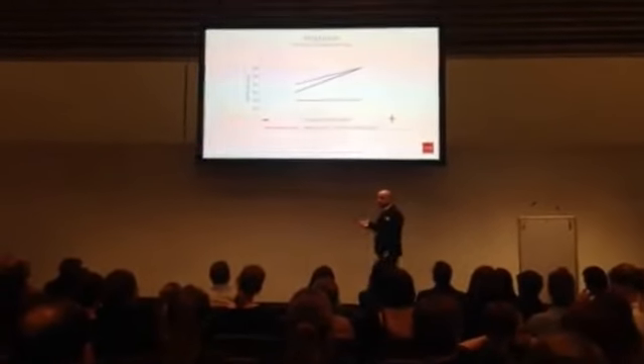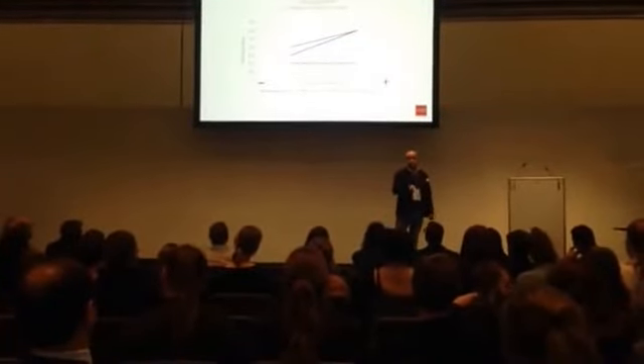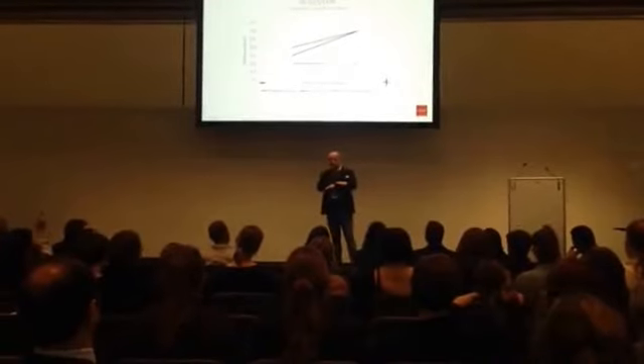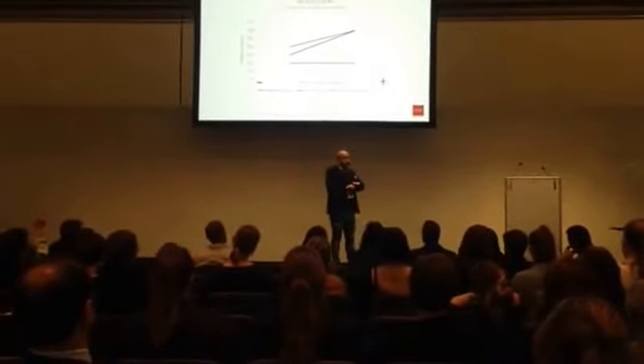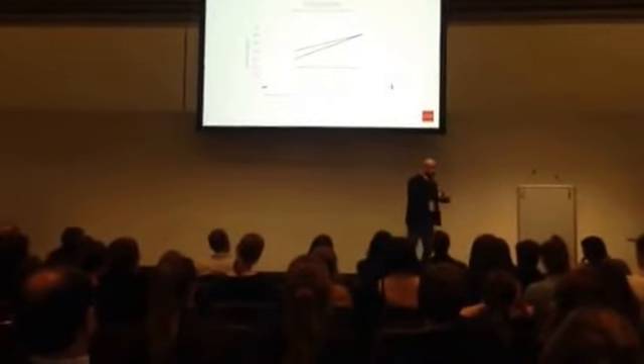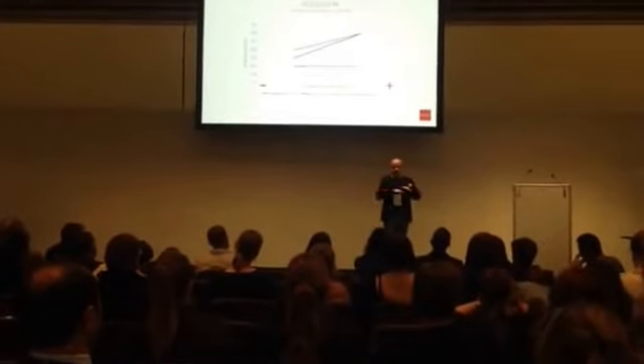What is wonderful is that with 3D printing, we can go down to 0.2 millimeter, which is that resolution, but it's constant, whatever the surface size, because there is no mold to fill. We do not have to fill a mold with liquid metal. We just have to print layer by layer, to grow something layer by layer.